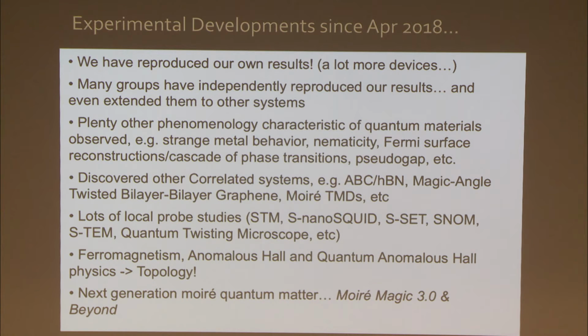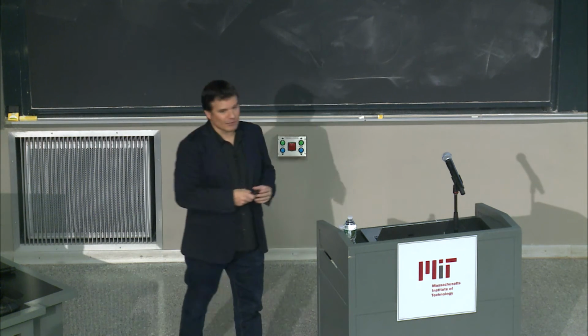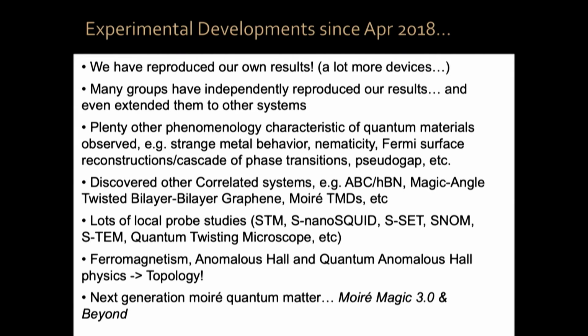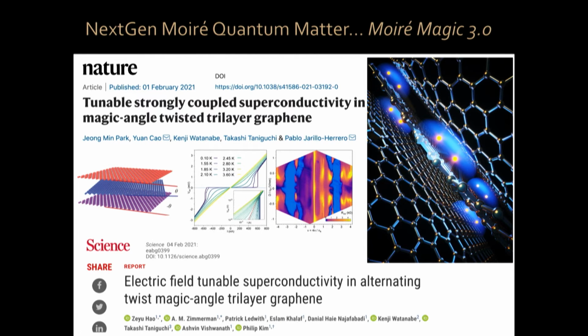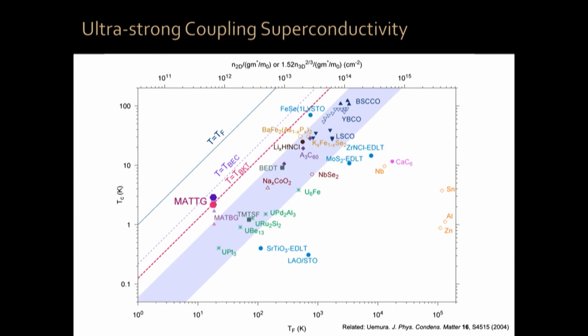Now, the other thing that is happening is that we're making what I call the next generation Moiré quantum matter, Moiré Magic 3.0 and beyond, 4.0, 5.0. Okay, so what does that mean? Well, last year, again, papers published back to back. You can see there's a lot of competition in this field. Papers appear in duos, in triples, in quadruples. So the group of Philip Kim and my group in the same week, we reported back to back in Science and Nature the discovery of a new superconductor, magic angle twisted tri-layer graphene. So now it's 3 layers with a different magic angle, okay, which leads to superconductivity. This happens to be actually the strongest superconductor in the world. Okay, what do I mean by that?